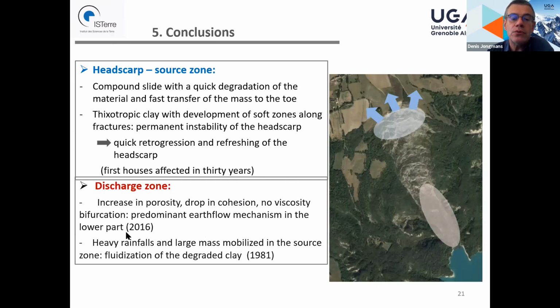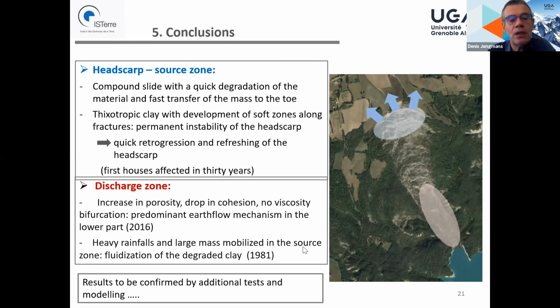And the second set of conclusions concerns the lower part of the landslide. So we have an increase in porosity, a drop in cohesion, and no viscosity bifurcation. So that explains that the main mechanism is earth flow with slip surfaces, with deformation located on slip surfaces in this lower part. And it's just in very specific conditions, where we have some heavy rainfalls with snow and a large mass which is mobilized in the source zone, that we may have some fluidization of the degraded clay.